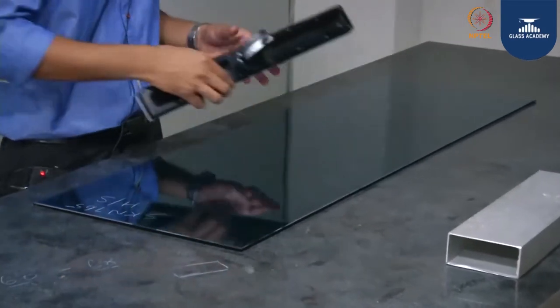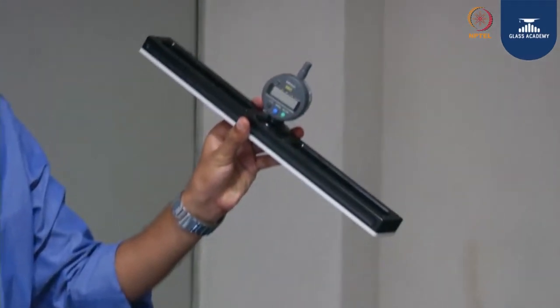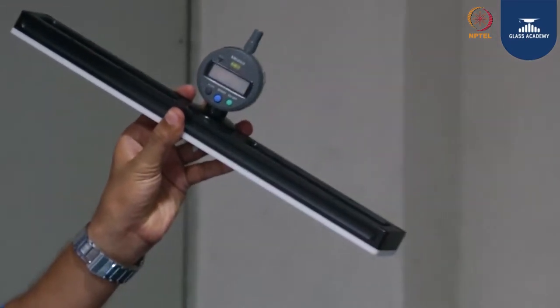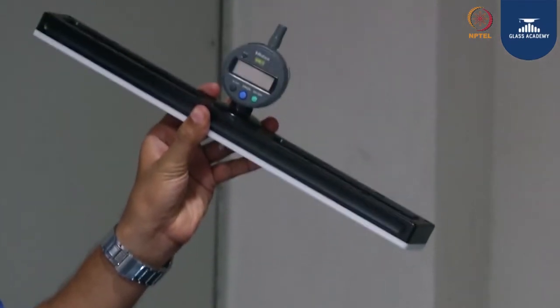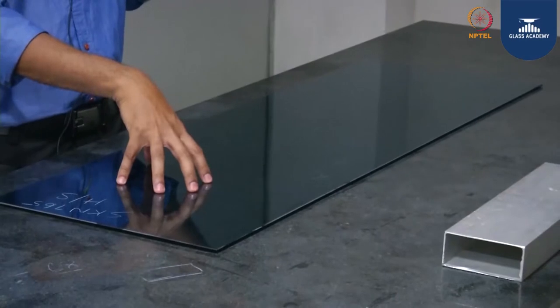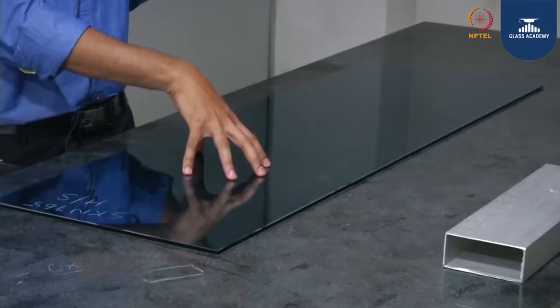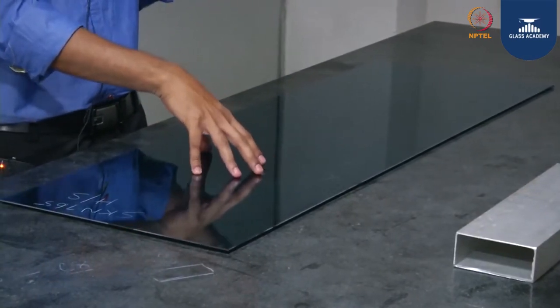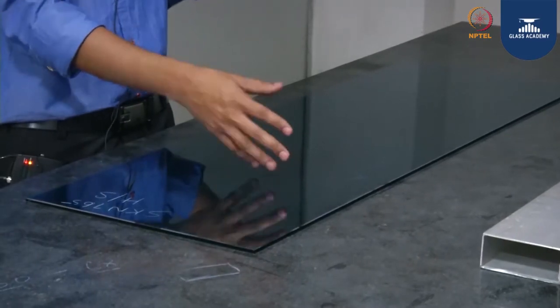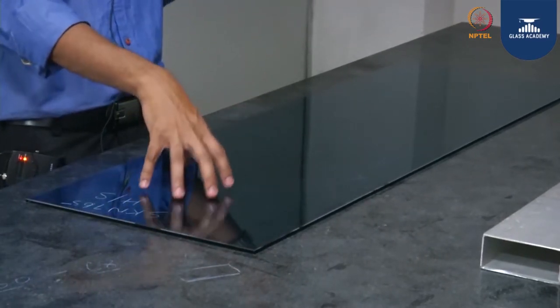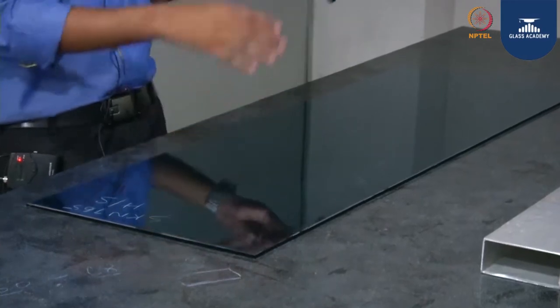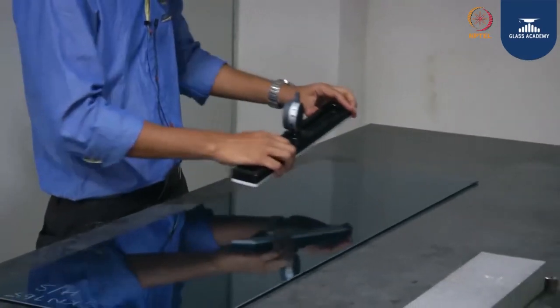In order to perform the roller wave, we need to have a roller wave gauge. We need to have a 1100 by 360 glass sample, and we need to make sure the glass is kept with the tin side on top. As the glass is during tempering process, the tin side is touching the roller, so we will get a roller impression on the tin side. Now we are going to measure the roller wave on the glass.